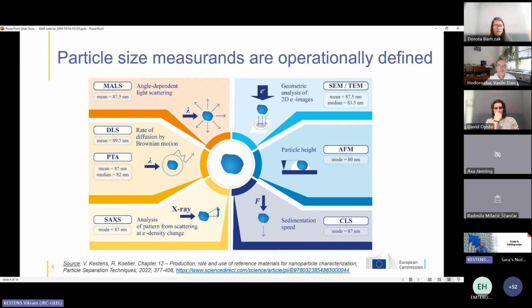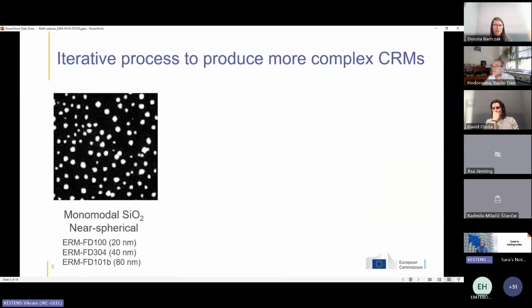Results, for example, obtained by dynamic light scattering for the same particle would result in 89.5 nanometers. But with particle tracking analysis, you could have results ranging from 82 nanometers to 87 nanometers. Or when you would measure the same particle with atomic force microscopy, you would measure 80 nanometers. So there are some differences, and these differences can be explained because, again, these particles do not have a perfectly spherical shape, and that means that they have many different external dimensions. And on the other hand, the methods are relying on different physical measurement principles. And for that reason, we are certifying different sizes.